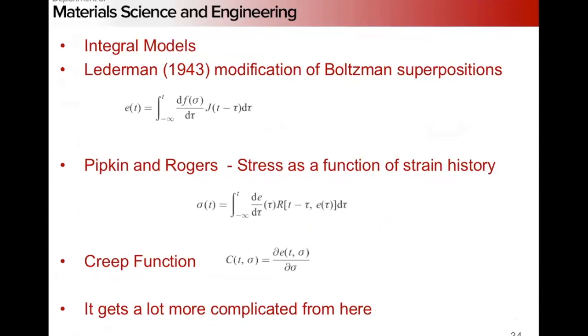Then the other approach are this huge family of integral models, right? Where basically you make one approach. What Lederman did is make modifications of the Boltzmann superposition by putting a explicit stress dependence in. Pipkin and Rogers wrote stress as a function of the history of strain, right? And then if you do that, you can get what he calls a creep function, which is a generalization of a compliance term, right? And then basically it gets a heck of a lot more complicated from here as you go out, right? There's integral models with dozens of terms in there that are sort of all sort of fit.